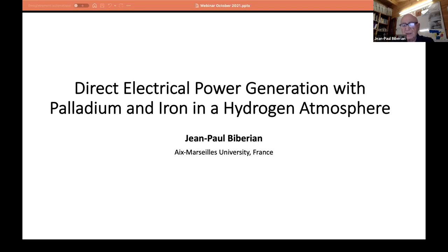and then electricity. A few months ago, an American scientist called Frank Gordon sent me an email telling me that he has produced electricity with a palladium film on a metal rod, in hydrogen. Basically, he was depositing palladium on the outer surface of a tube. Then you have the second tube, and the two tubes are isolated from each other, so there's no electrical contact between them. When he put hydrogen in it, he observed a voltage and a current without anything. There's no contact. So he doesn't understand what's happening.